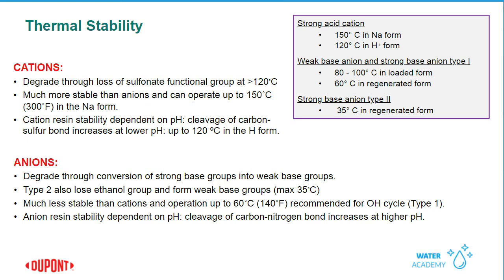Resin analysis is a good way to check the health of these resins, to be able to see what's going on and if they have been degraded at all. So again, anion resins don't have a high level of thermal stability, so care always needs to be taken with regeneration temperatures to get the most lifetime out of your anion resins.